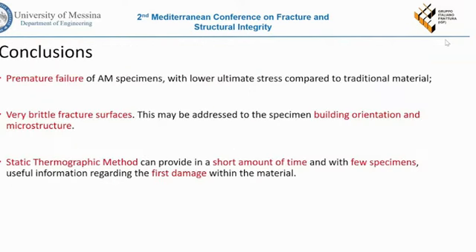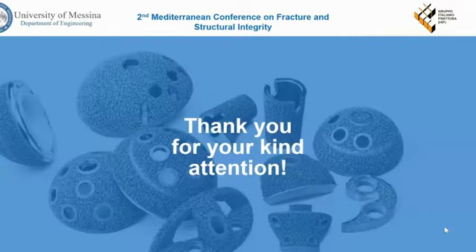So in conclusion, as we have seen, we have a premature failure of the additive manufactured specimen with a lower ultimate stress compared to the traditional material. We also see a very brittle fracture surface, and this may be attributed to the specimen building orientation and microstructures. And we also showed how, with the static thermographic method, we can obtain usable information about the damage initiation in the specimens with a very rapid static tensile test. Thank you for your attention.